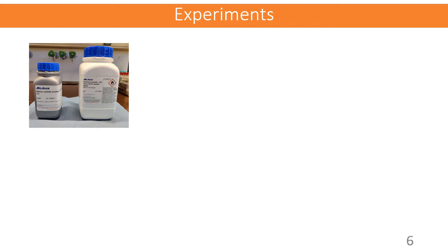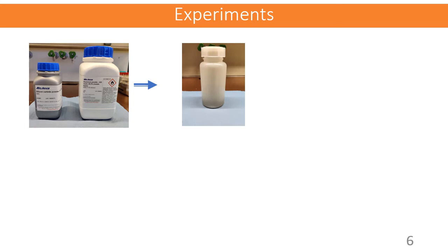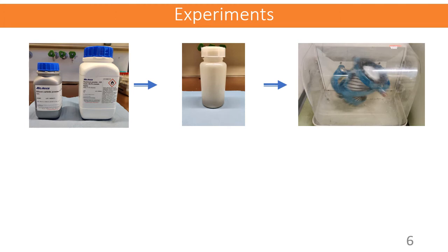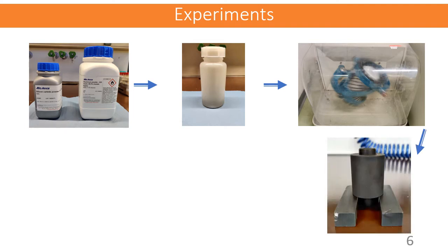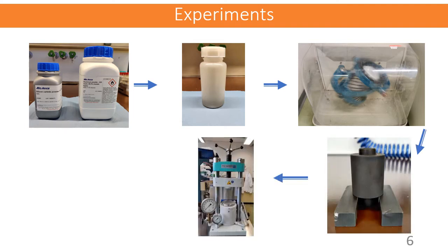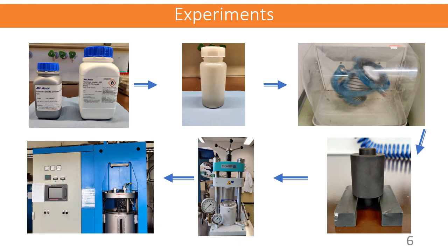Moving on to the experiments, we procured the initial powders from the industry. Depending on the composition, the powders were weighed in this plastic bottle. Zirconia balls were added in this plastic bottle and were mixed using a tumbler mixer to get homogeneous powder distribution. After that, the mixed powder was introduced into the graphite die. This graphite die was pre-compacted at a particular pressure so that we get sufficient green strength in the green compact. This green compact was later sintered in the modern spark plasma sintering technique, where simultaneous application of pressure, temperature and DC pulse current is generated. So we get a very good densification along with short processing.